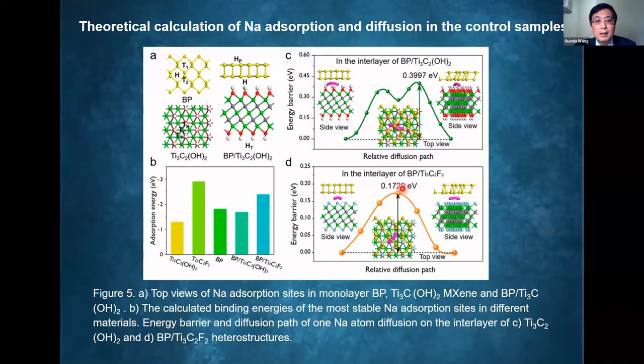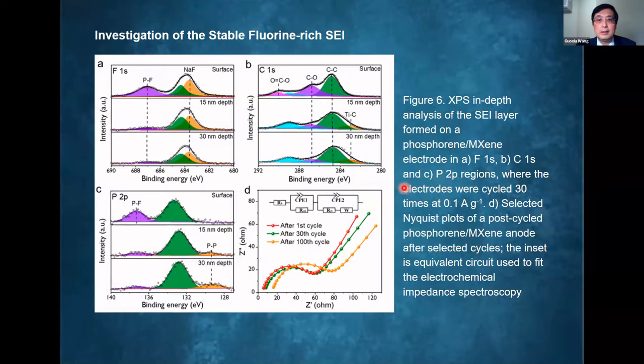We found that the MXenes have a very strong adsorption energy towards sodium ions. And particularly we did in-depth XPS profiling, and we identified that fluorine participates in the SEI layer formation. The fluorine is brought in by the MXene because when you etch the MAX phase, you naturally bring fluorine and functionalize the surface of the MXene with fluorine termination functional groups. So the fluorine brings the benefit of stabilizing the electrode and then extending the battery cycle life.